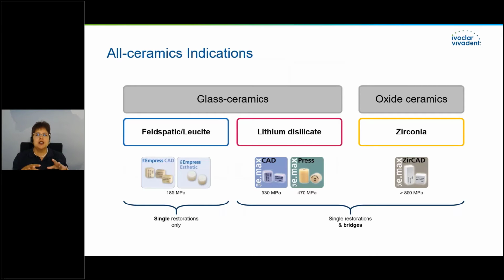aesthetic. So regarding the all ceramic indication, we can sum up that due to the low flexural strength of 185 megapascal of IPS Empress CAD or IPS Empress Aesthetic, they are indicated only for single restorations. On the other hand, we have lithium disilicate, like our IPS Emax CAD or IPS Emax Press, with a flexural strength higher than 470 megapascal. And they are indicated together with our zirconia material, which are higher than 850 megapascal, for single restorations and bridges. The difference is only that here the lithium disilicates are indicated until the second premolar, and our zirconia material are indicated for the complete jaw.